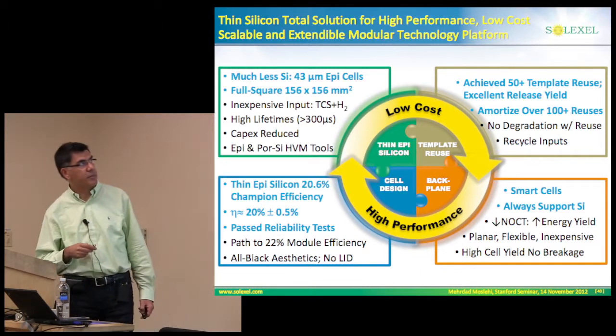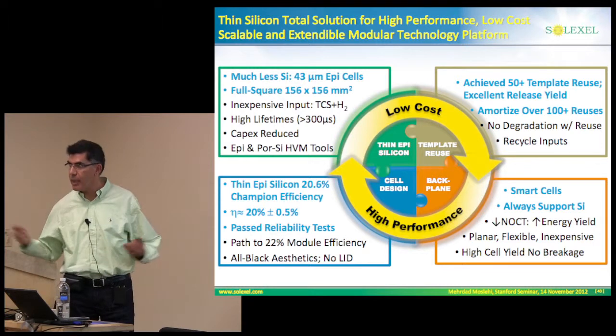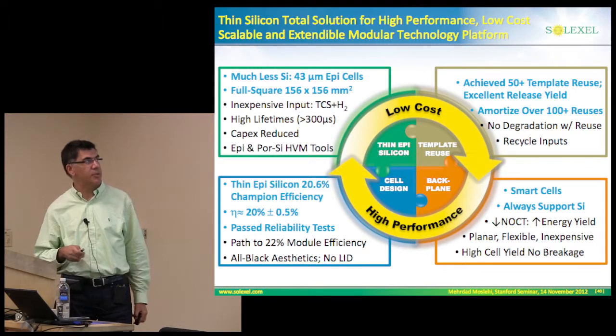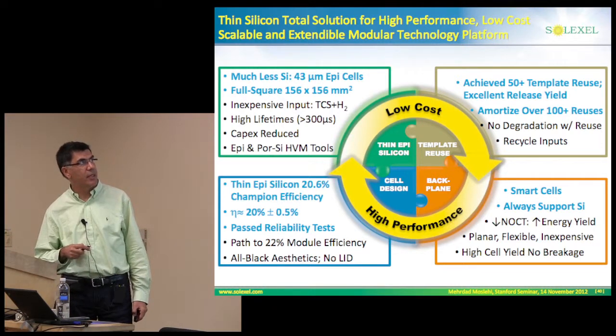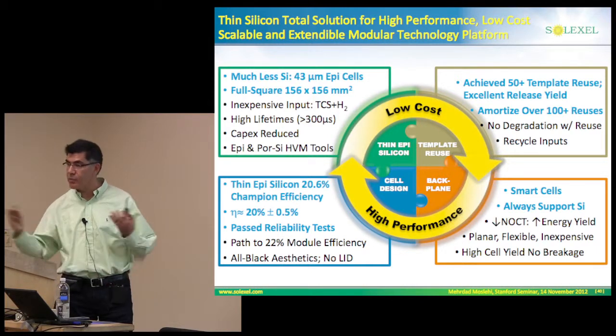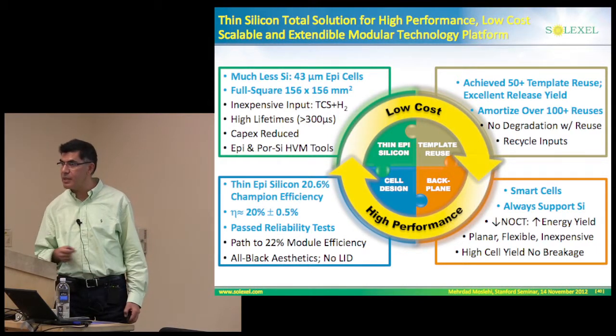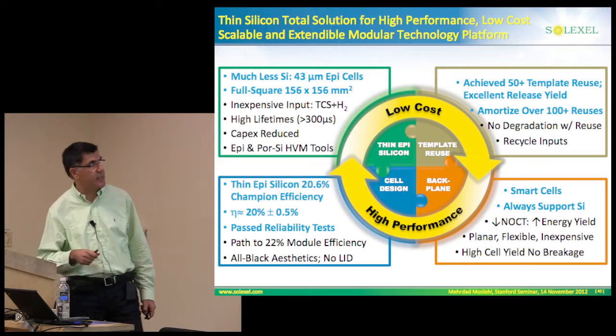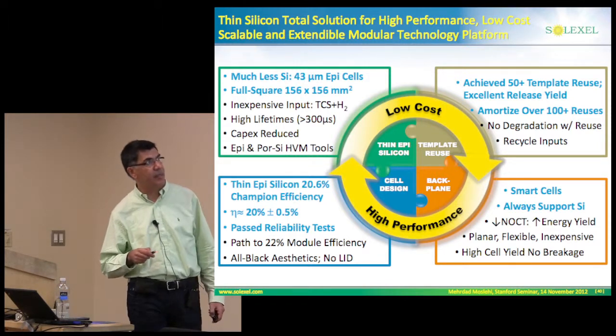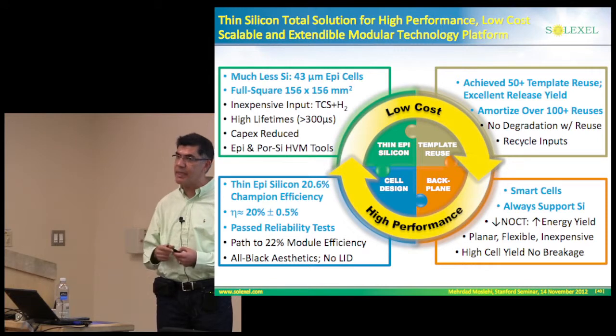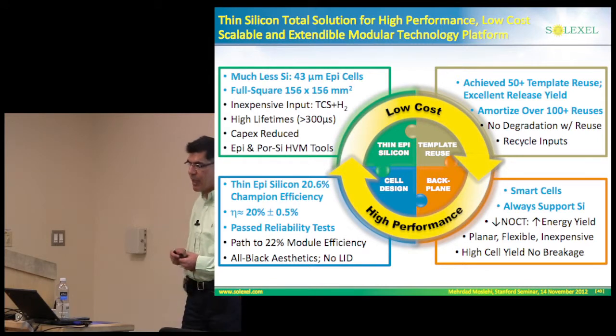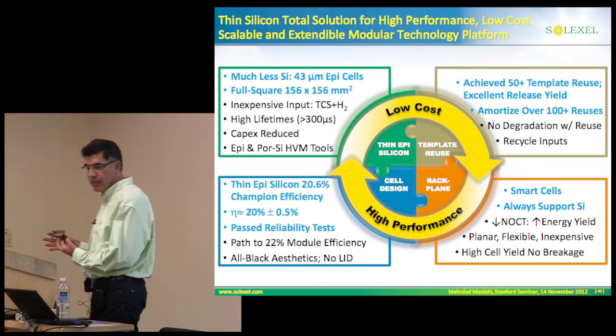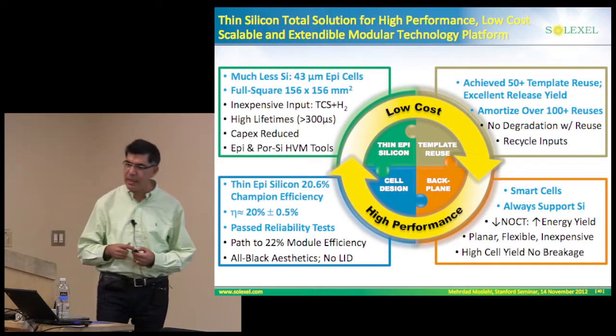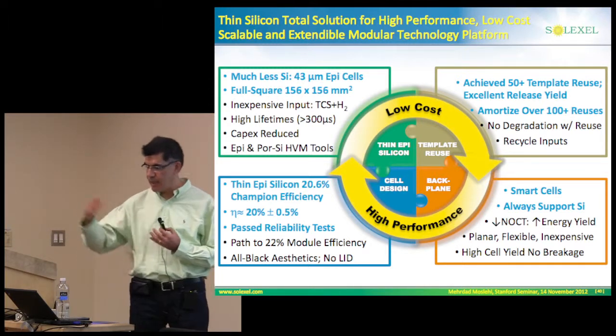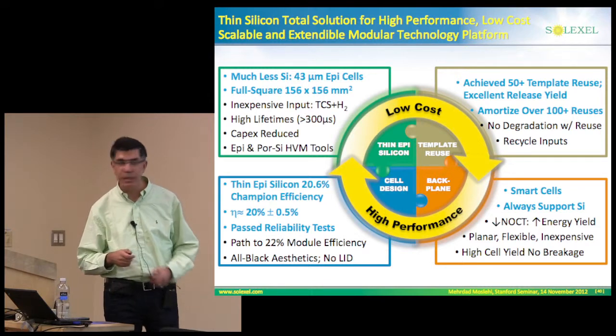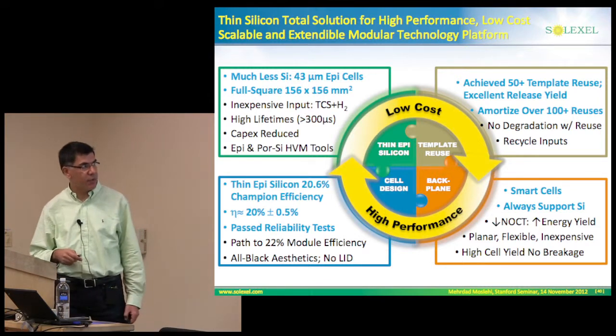And I showed you that we substantially reduce silicon consumption with our 43 micron epi cells. We make the world's largest back contact IBC cells with our full square cells. And template reuse is a very important enabler for this value proposition. We have done over 50 reuses, and we see a clear roadmap to get over 100 reuses as we go forward.